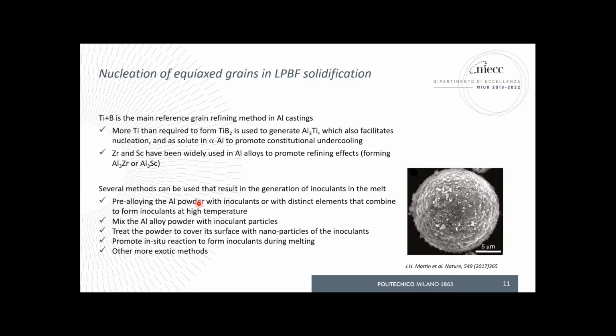Or we can use some elements that will combine during solidification or after the process of atomizing the powder to produce the inoculants. We can simply mix the aluminum powder of the starting alloy with the powder of the inoculants. There has been some works in the literature. I also will show you some information about that, some results coming from this strategy.